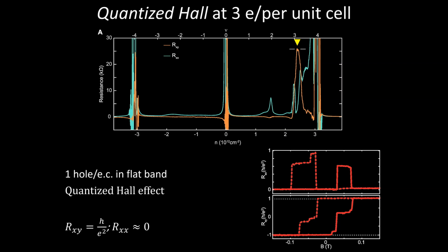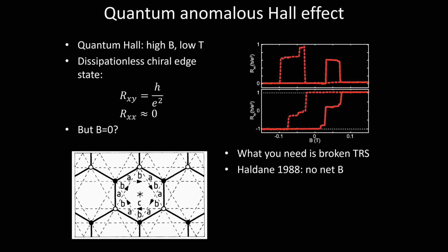Okay, but instead of happening at high magnetic field because of Landau level physics, it happens at 0 magnetic field. Okay, and it turns out this is an example of a quantum anomalous Hall effect, which is an idea that goes back to the 1980s. After the discovery of the integer quantum Hall effect, Duncan Haldane asked the question basically, do you need to have a magnetic field? Is that essential, right? You need to break time reversal symmetry. That was understood well, because if you don't have broken time reversal symmetry, then the Hall conductivity has to vanish. But he came up with a model, it's kind of a complicated model to understand how to do in an experiment, but basically said you don't really need a net magnetic field.